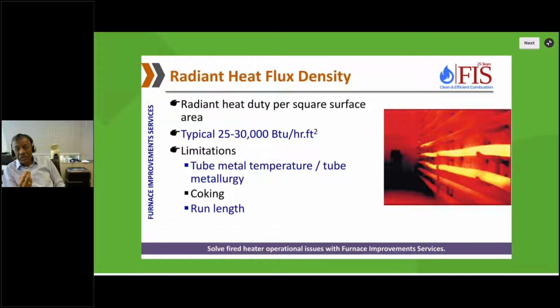So one important parameter in the radiant section is radiant heat flux density. And it's basically heat duty per unit area. Now in cracking furnaces, if you see the history of 50 years, how the cracking furnaces have evolved, most of the developments which have taken place are due to improvement in the tube metallurgy. The metallurgists have worked very hard, and they have come out with exotic alloys which can allow us to go to almost 2000 degree F or 2100 degree F metal temperatures.